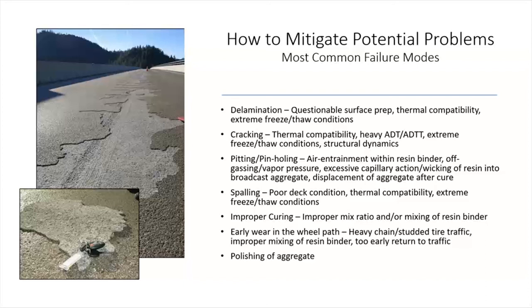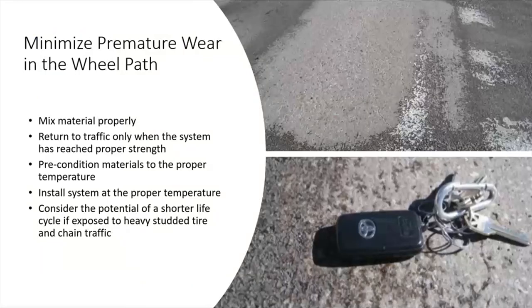They really bought in. Excessive wheel wear on the wheel path, I'll talk quickly a little bit more about that, but heavy chain and studded tire traffic is a consideration, and so is mixing and returning to traffic too early. You want to make sure it's fully cured. You start putting traffic on there and it starts breaking down the areas that are still cross-linking, and then you put chain tire traffic on there and you start wearing early and polishing of aggregate. Some aggregates are more polish resistant than others.